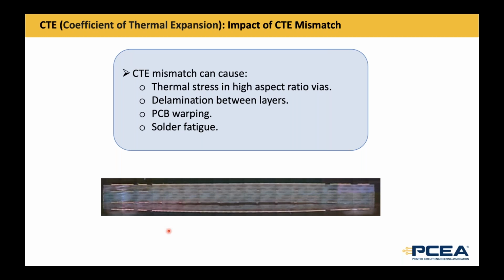So the answer to the first question is it's often been tried to measure, using a method like TMA, the differences in different areas of a circuit board, depending on the copper loading, depending on the plated through hole loading. And it's not a very good way to do it because the probe is about 5 millimeters. Some of the probes are actually up to about 10 millimeters, and the features are too close together to measure the difference.